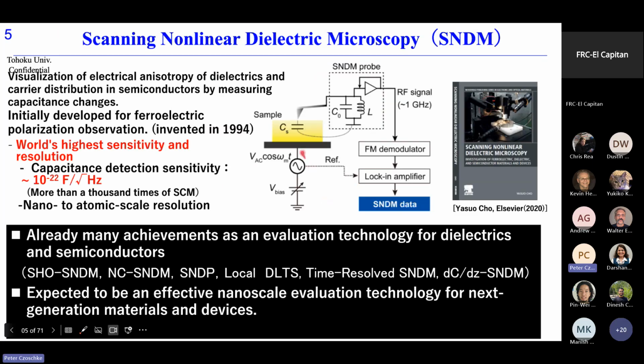With this background, about 30 years ago, we invented the scanning nonlinear dielectric microscopy, SNDM, which visualizes the electrical anisotropy of dielectrics and carrier distribution in semiconductors by measuring the capacitance change. Of course, this microscopy was initially invented for ferroelectric polarization observation.